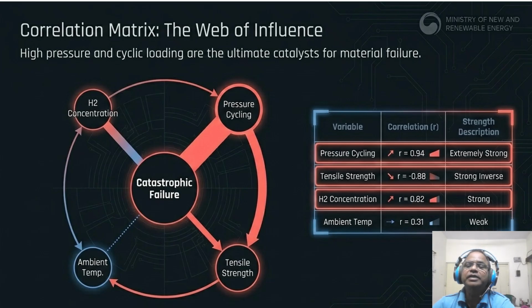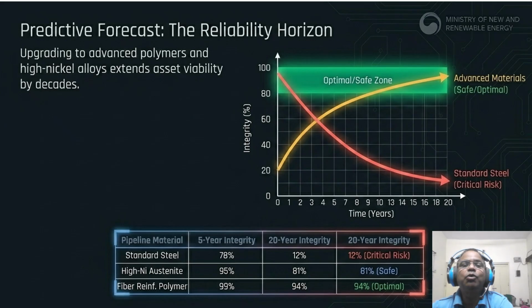Coming to our next slide, which is about predicting the reliability horizon. This graph shows the integrity percent over a 20-year period. The red line represents the standard steel. Notice how it plummets to 12% integrity, a critical risk zone, by year 20. Now look at the green curve for the advanced materials, fiber reinforced polymer and high nickel austenites, which stay well within the optimal or safe zone. High nickel austenites maintain 81% integrity after two decades. Fiber reinforced polymers are even better at 94%.